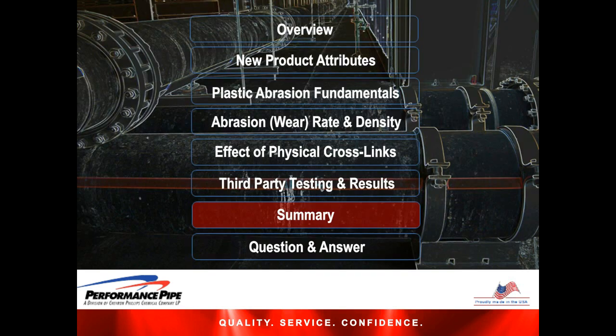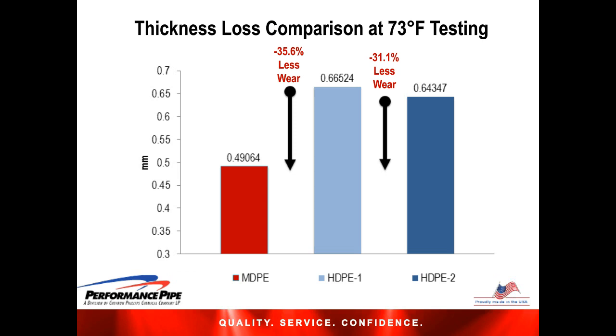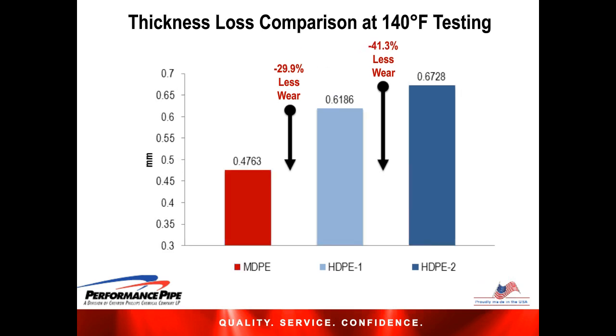So to summarize our findings and looking at the same abrasion data in a little different way, this is now looking at essentially thickness loss, which in terms of a pipe conveyance system may be a more directly relevant way to look at it. And again, of course, as expected, the data shows the same trend. The medium density pipe is better in terms of abrasion resistance compared to either of the two high densities by a factor somewhere around 30-35%. And this is data at 73 degrees Fahrenheit. And then the same type of data for the 140 degrees Fahrenheit test shows the same general trend with a range of anywhere from 30 to 40% improvement relative to the two high-density resins.